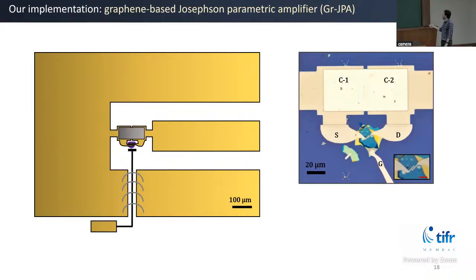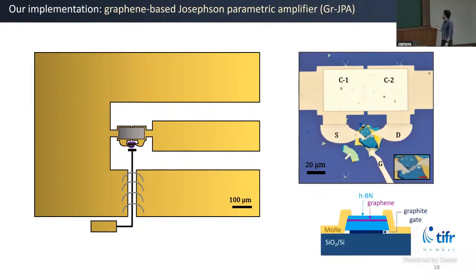So this is an optical microscope image of our device. There are two parallel plate capacitors and the Josephson junction, and they are in parallel, so they form this LC resonator. In addition, what we have here is this back gate. It dopes the graphene and helps us to tune the critical current of the Josephson junction, and eventually the resonance frequency because you are changing the L.